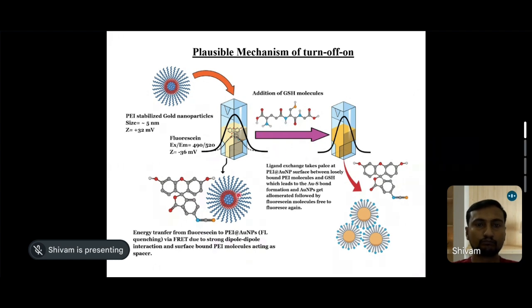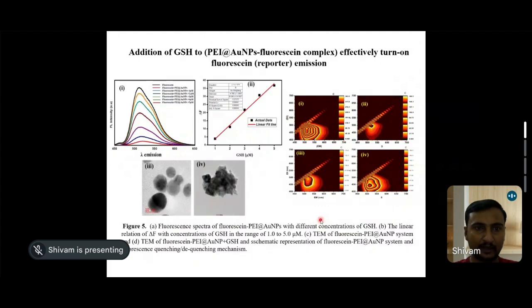But after the addition of glutathione molecule, a ligand exchange takes place at the PEI stabilized gold nanoparticle surface by loosely bound polyethylenimine molecule, which leads to the gold-sulfur bond formation. AuNPs get agglomerated, followed by the fluorescein molecule being free to fluoresce again. Here you can see the gold nanoparticle gets agglomerated. Here you can see after addition of glutathione, the nanoparticle gets agglomerated.